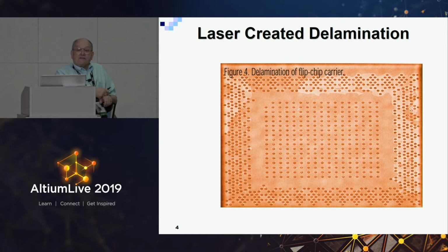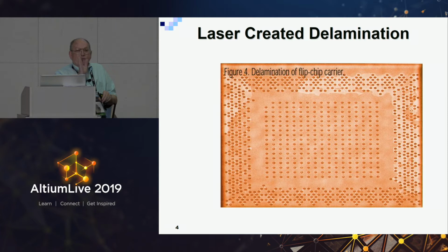The other thing is the use of CO2 lasers. One of the problems with CO2 lasers is they can induce interlayer delamination because of the CO2 energy level. So it's very critical, the narrow band of how much energy and pulses a laser can put out between removing the resin and creating so much heat it does micro delamination that you can't see. And you do not want micro delamination, because that will cause your board to fail in the field. And you don't want failures under warranty and things like that. It gives your company a bad reputation.